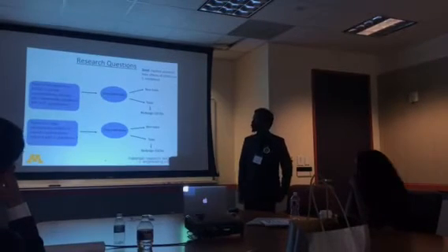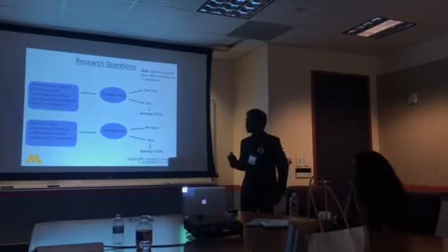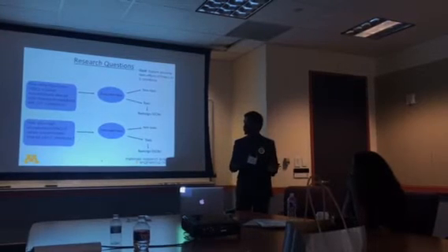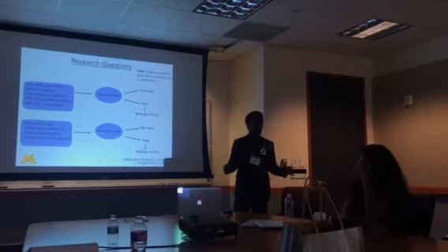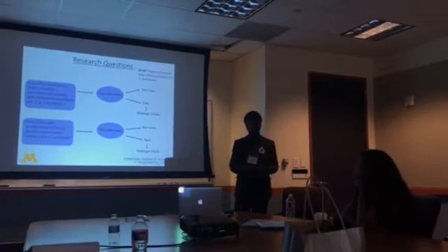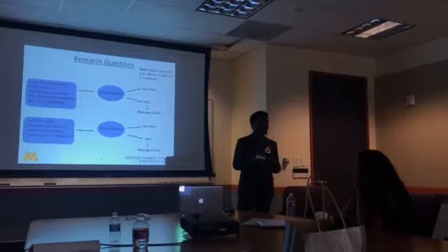So the research question being addressed: how will the P-type boron-doped silicon nanocrystals in varied concentrations interact with Shewanella oneidensis? Or how would the N-type phosphorus-doped silicon nanocrystals in varied concentrations interact? Why do we want to vary their concentrations? Because when we vary their concentrations, we change the luminescent property. So we don't have to actually change the size of the particle, but we increase the concentration of the dopant, and then we go ahead and observe this photoluminescence property.